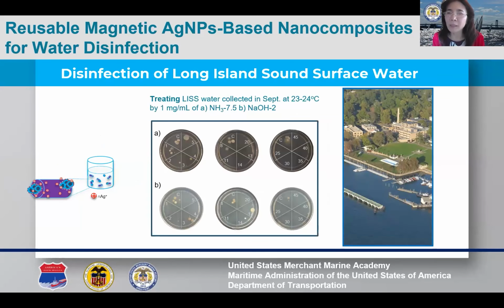The feasibility of applying the nanocomposites for disinfecting Long Island Sound surface water was also investigated. Long Island Sound surface water samples were collected and treated with 1 milligram per ml of Ammonia 7.5 and Sodium Hydroxide 2 nanocomposites. The plate results presented here confirm the absence of viable microbes in these water samples after 20 minutes of treatment. While our previously reported MS-Ag nanocomposite achieved similar antimicrobial results, the mesoporous nanoplatforms significantly reduced the silver leaching by a factor of 10 to 1,000.